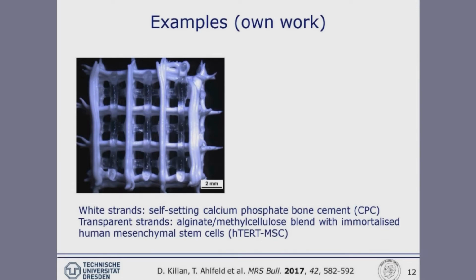One example from our own lab: here we tried to generate a completely open porous structure designed for bone tissue engineering. So we have replaced the thermoplastic polymer PCL by a self-setting calcium phosphate bone cement, a material we have worked quite a lot on in the last couple of years, and published already a few papers on using this for 3D printing. And yeah, you can nicely see here the cement and a rather stiff cell-laden hydrogel, which I will speak about a little bit later, so that we still have open macropores, which of course are helpful for oxygen and nutrient supply to the cells.